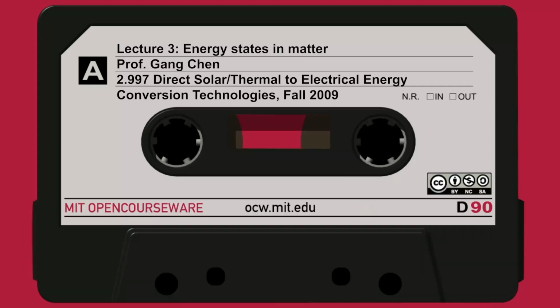Yes, but that's exactly how it absorbs. You need a phonon, right? The phonon has that wave vector, but the phonon doesn't have enough energy, its omega is too small. So phonon plus photon: the phonon gives you the wave vector, the photon gives you the energy, and you can lift from here to here.